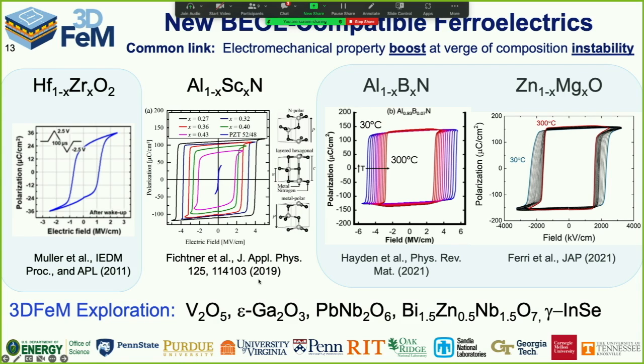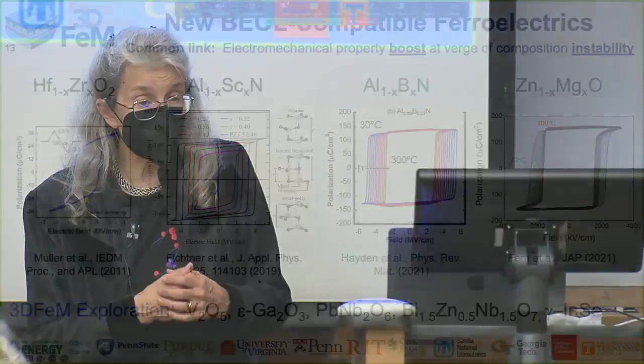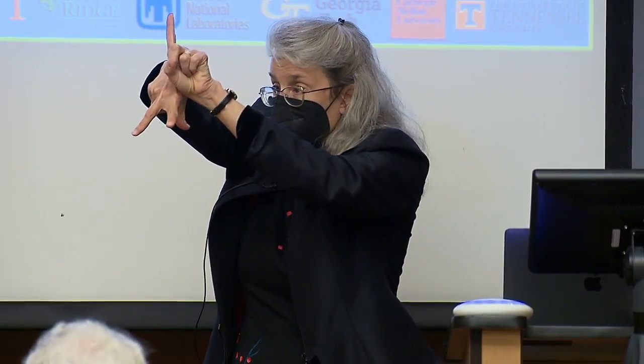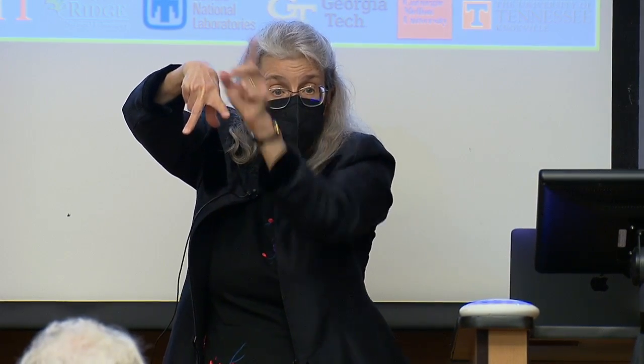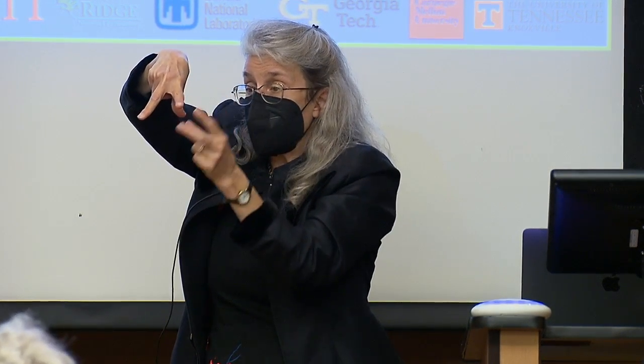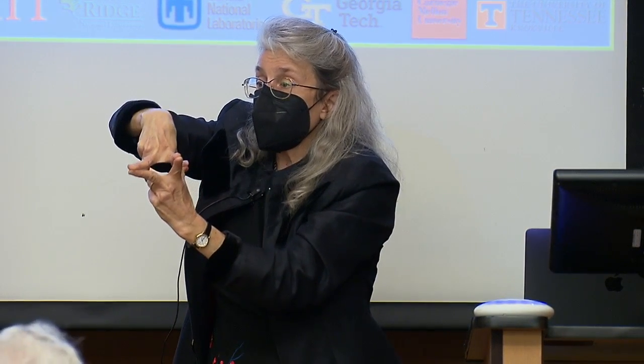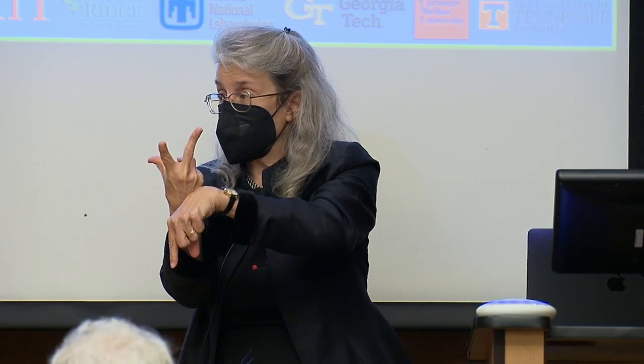This is the Wurtzite structure. In the Wurtzite crystal structure, I have tetrahedral coordination on the cations in question. So one neighbor up, three neighbors down at an angle like this. And in order to switch it, I have to take that atom, force it through the space between the three atoms below it, and invert the direction of the tetrahedron. So that's how this material switches.